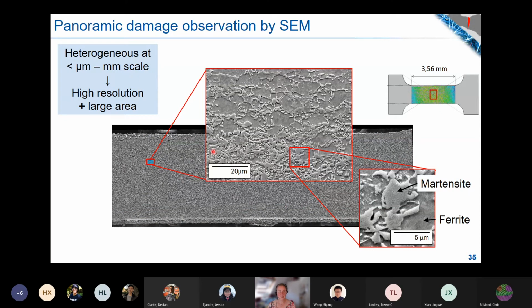So you can already see, this is actually looking on the top of the sheet. This is a dual phase steel. The bright parts are the martensite. You can see where there are only some islands and a lot of ferrite, and we also have regions where there is a lot of martensite. These were the martensite bands that you saw from the side. So this is one of the reasons why, if we just look at one image like this, we fear we might not be representative enough. So we look at panoramic images that are maybe a square millimeter in size.